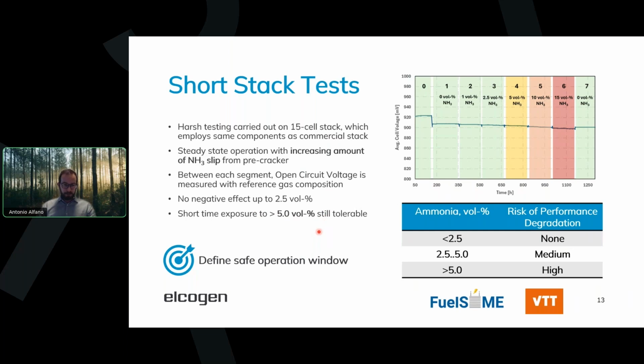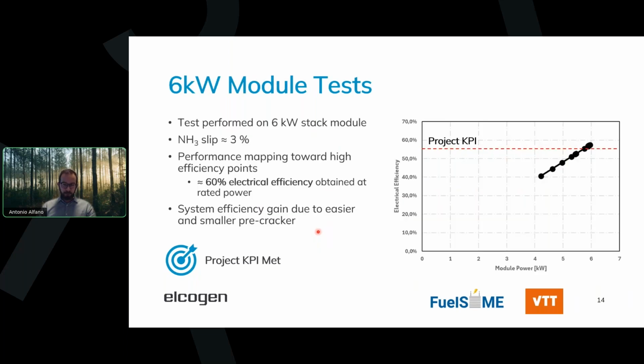From here, we then went one step forward. Taking the information from here, we went to this 6 kilowatt module, where we used around 3% of ammonia in the fuel inlet composition. The rest was cracked with the pre-cracker unit. And then we started doing some performance mapping. And what we were able to achieve was to meet the project KPIs in terms of electrical efficiency. At stack level, we have achieved at the rated power, which was 6 kilowatt, close to 60% of electrical efficiency.